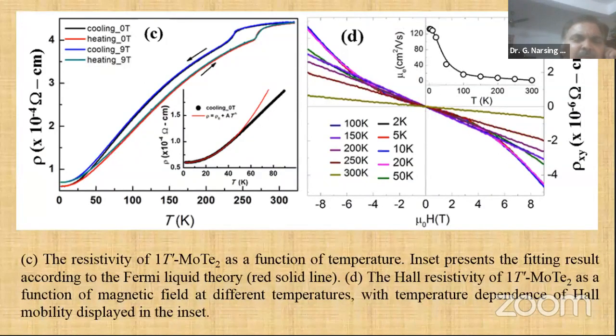So here it is 1T prime. You can see there is no change with or without magnetic field, but only the cooling and heating curves differ. That is the first order phase transition from 1T prime to Td. If there is hysteresis it is first order; if there is no hysteresis, it will be second order. That's an important point. So this is a first order transition. If you make the IV curve, you will get the mobility parameter, and that mobility is almost 4 times less compared to that one. So this is the 1T prime material.